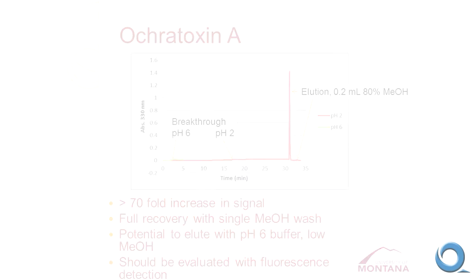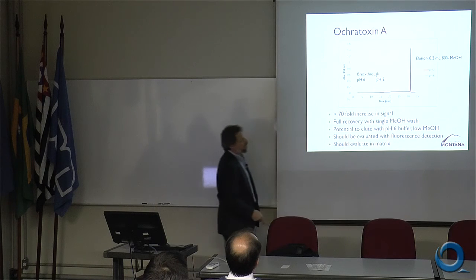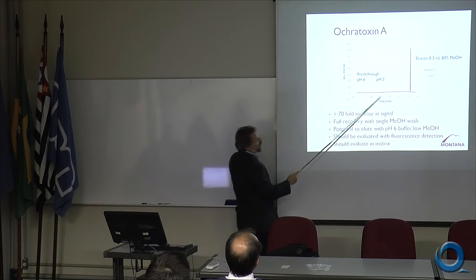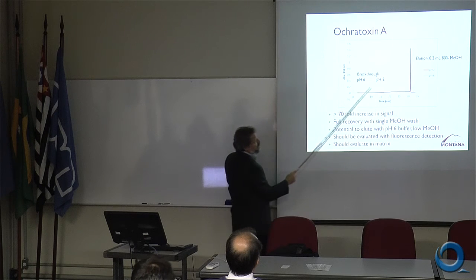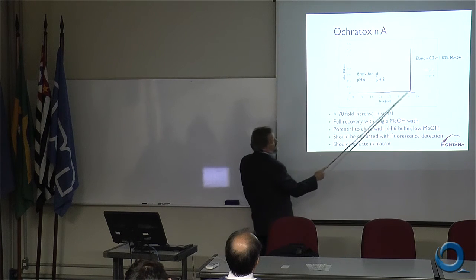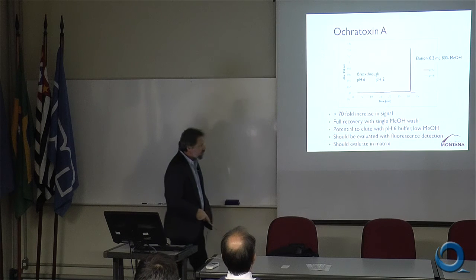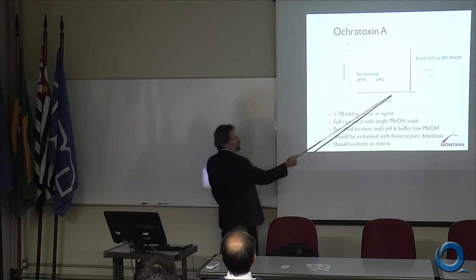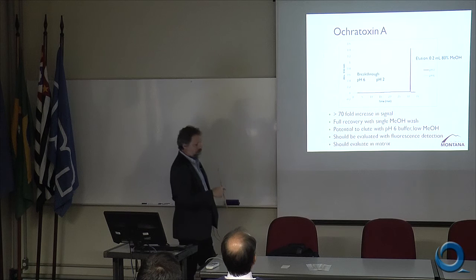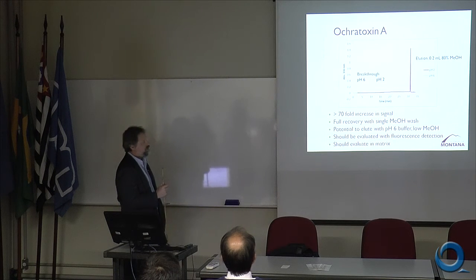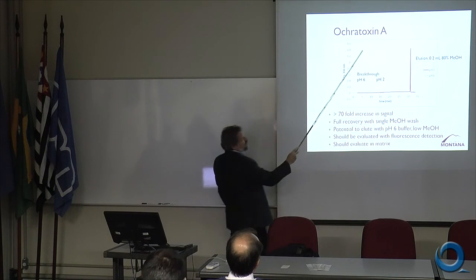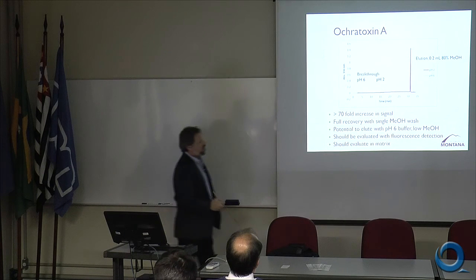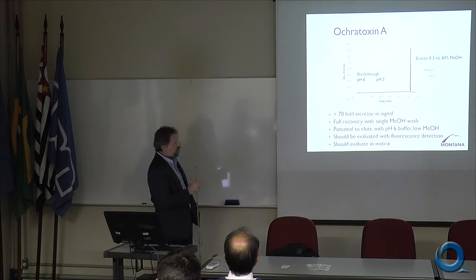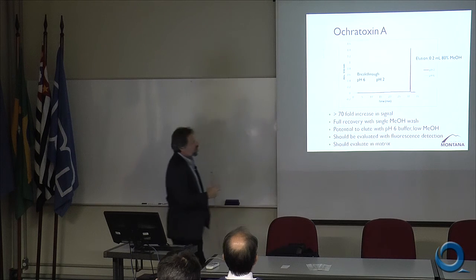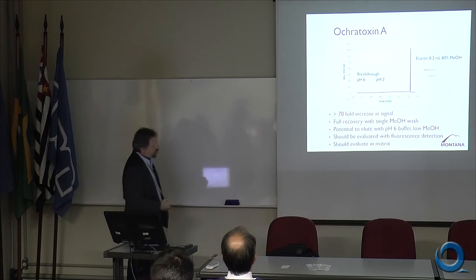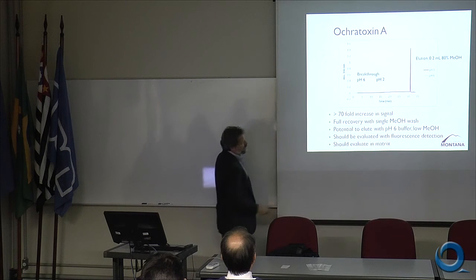And then if we make a single injection, 0.2 milliliters of 80% methanol, we get all of this compound that was retained in this region here, all of the ochratoxin A, off in a very sharp peak with an increase in the signal of about 70-fold. So we're getting a concentration increase of at least 70-fold. This is absorbance of 1.4, so I doubt that it's in the linear region of the detector. So we may actually be seeing a greater concentration factor than we see in signal.